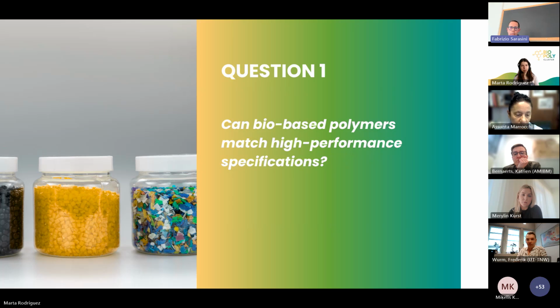Okay. As Frederick was mentioning, yes, it depends on the sector that you want to explore. Because in some cases, for instance, rigid packaging, conventional bio-based polymers are already comparable with traditional fossil-based plastics. The problem is when we want to explore different sectors, much more challenging, like, for instance, the automotive or even aerospace or high temperature electronics, because currently these bio-based polymers suffer from lower thermal stability, an excess of moisture sensitivity, and especially in some cases processing challenges. And this is still limiting their industrial use.